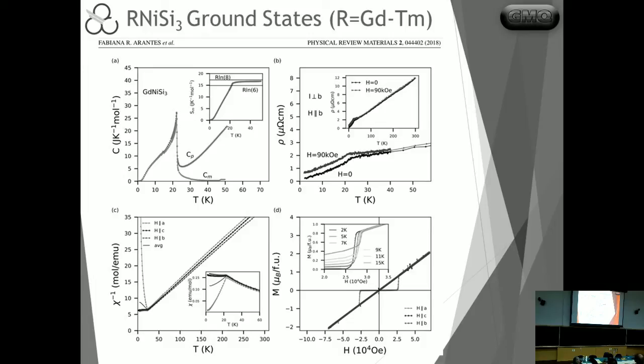All of these materials turned out to be nice metals, right, with very low resistivities, very high RRRs, which attest the crystallographic quality. From specific heat, we could find out what was the entropy involved in the ordering, which tells us about who is actually participating, right? So in the case of gadolinium, you can see that all of the states of the J equals 7/2 multiplet are there participating in the transition.